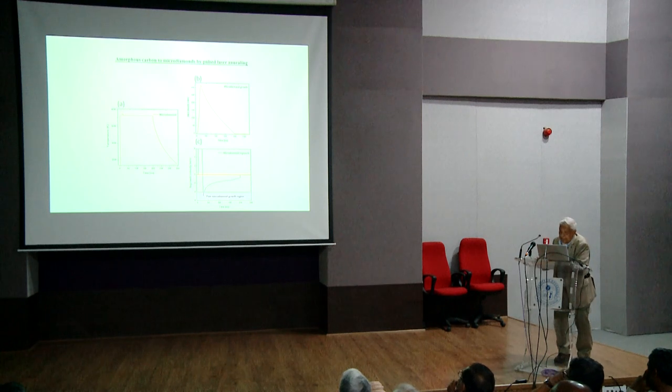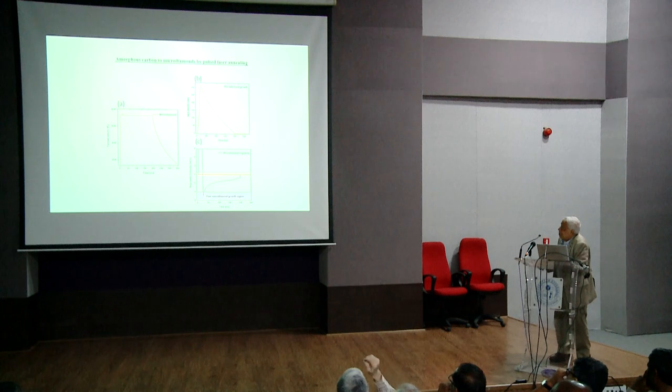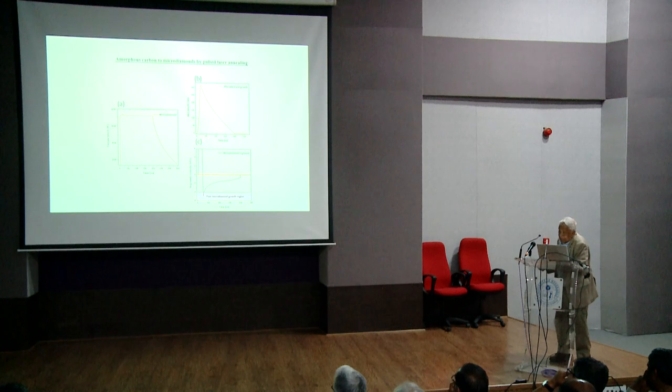Now, many of you are wondering about the laser-solid interactions. You can see this is the temperature versus time. You rapidly, within a few nanoseconds, go to very high temperature, and then you quench it. If you look at the melt depth versus time, this is the melting, and this is the solidification. And this is the differentiation of this. That gives you the growth velocity.